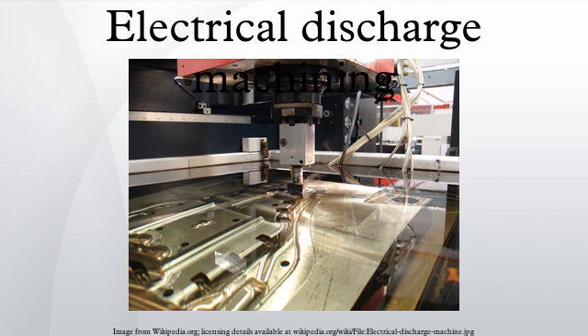Wire cutting EDM is commonly used when low residual stresses are desired, because it does not require high cutting forces for removal of material. If the energy power per pulse is relatively low, little change in the mechanical properties of a material is expected due to these low residual stresses, although material that hasn't been stress-relieved can distort in the machining process. The workpiece may undergo a significant thermal cycle, its severity depending on the technological parameters used. Such thermal cycles may cause formation of a recast layer on the part and residual tensile stresses on the workpiece. If machining takes place after heat treatment, dimensional accuracy will not be affected by heat treat distortion. Applications: prototype production.